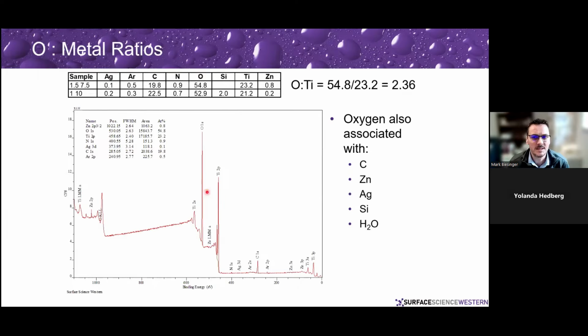What do I mean by that? So this I believe was a titanium or an apatite type sample that had a whole bunch of different species on the surface. We wanted to know from the survey spectra how things were changing. They wanted to look at the oxygen to titanium ratio. It's a good way of looking at things. And so when you first look at this, you just plug in the numbers and go, I got so much titanium, so much oxygen, and I get a ratio of 2.36. It's like, well, okay. But that's not really true because there's oxygen also associated with carbon. There's oxygen associated with the zinc. There's oxygen associated with the silver, silicon. There could even be water present as well, which we want to know about. And so that number is wrong.